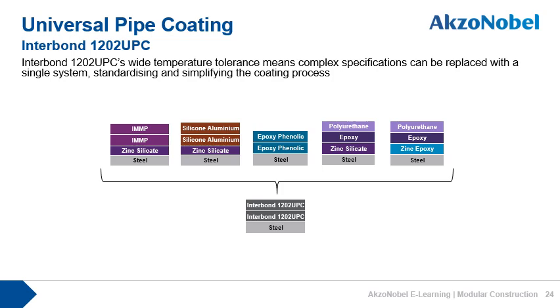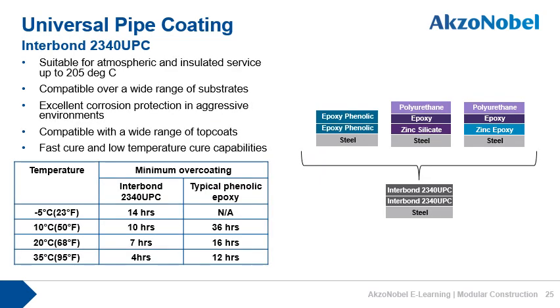So using the UPC products such as Interbond 1202 UPC, we can reduce the number of products used on high heat specifications down from 6 or 7 down to just 1 or possibly 2. With the 2340 UPC, similarly, we are able to replace multiple systems such as phenolic epoxies, traditional 3-coat zinc epoxy polyurethane, or even in some cases zinc silicates and aluminium silicone aluminiums down to just the Interbond 2340 UPC.